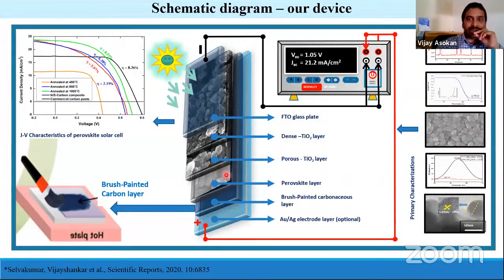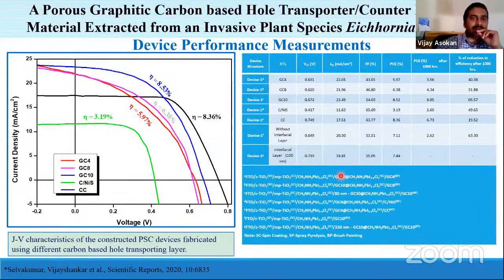Then the perovskite layer was formed here, and the porous titanium dioxide, which is needed for the electron transport layer. Here is the dense titanium dioxide and FTO glass plate. This is how we constructed our device. We have shown different primary characterization parameters of these devices with different annealing.